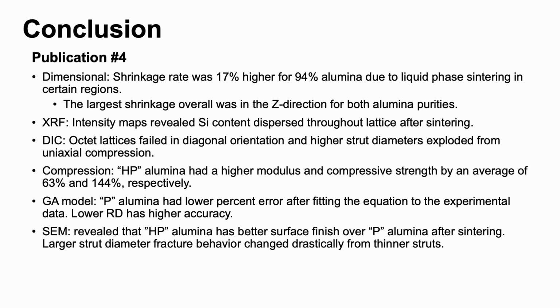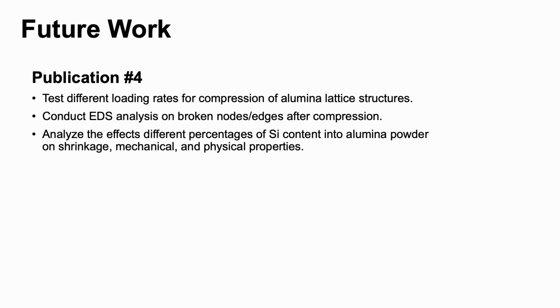When we looked at the images using SEM analysis, it revealed that the HP alumina had a better surface finish over P alumina after sintering. And we also saw that larger strut diameter fracture behavior changed drastically from thinner struts. In the future, for this work, I would suggest to test different loading rates for compressions of alumina lattice structures, since the standards that we used were based on metallic lattice structures.